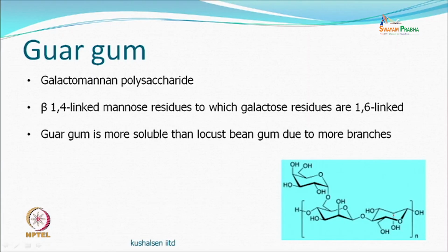There is another interesting compound which is not good for reactive dyes, but the important thing is that it has a very high molecular weight, and it has small, very regular branchings, so the structure is not very compact. If things are not compact, then water molecules can go inside, and washing can become easy. A very compact structure can even mean crystalline structures. Nothing can penetrate, dye cannot go into the crystalline region, water cannot go into the crystalline region, but this type of compound will be more amorphous.